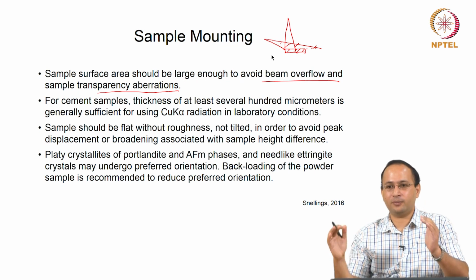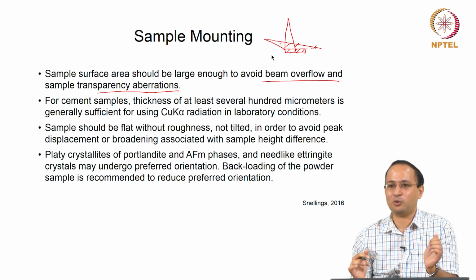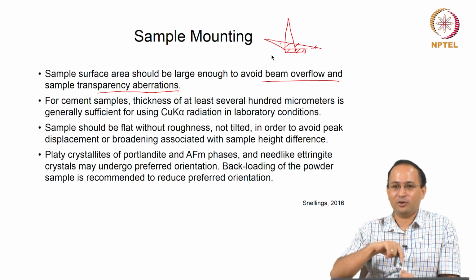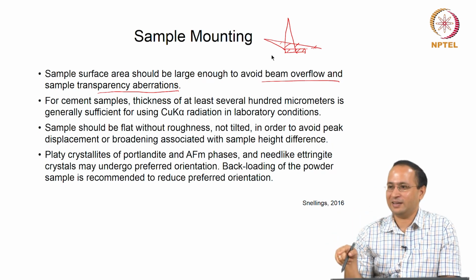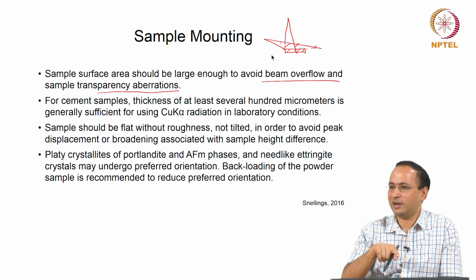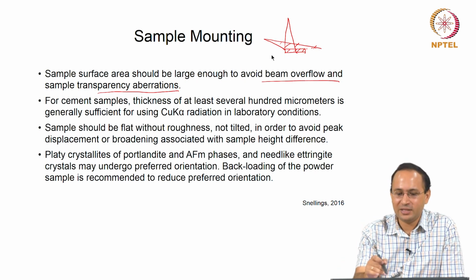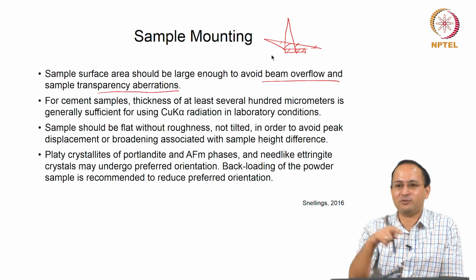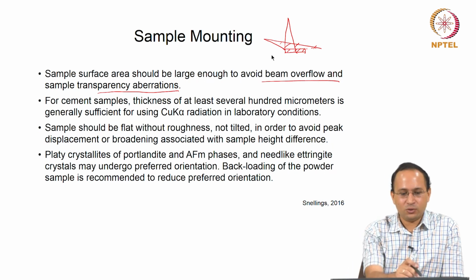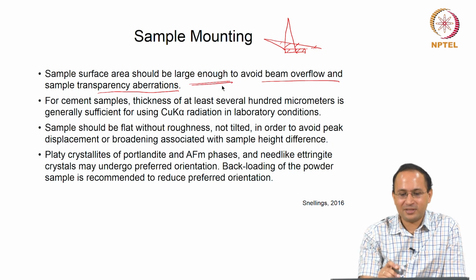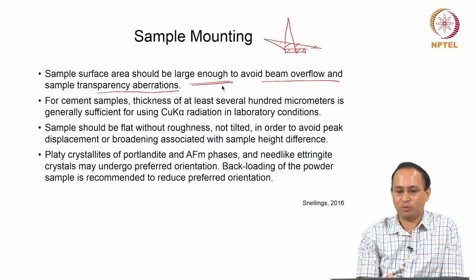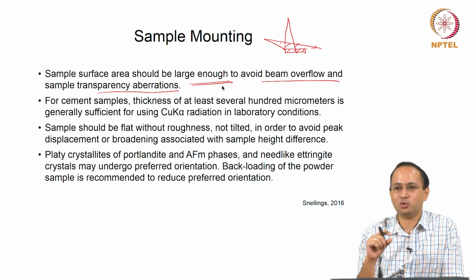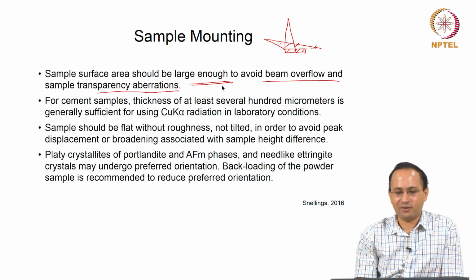Think of the X-ray diffractometer: you are moving along the circle, theta from smaller angles to large angles. So, these are the issues. You have to make sure you have enough surface area. That is why your sample surface area should be large enough to avoid beam overflow, and for sample transparency, it should have some thickness. A few millimeters of sample thickness is good enough for X-ray diffraction of cements.